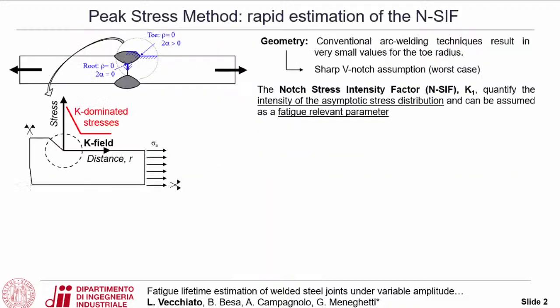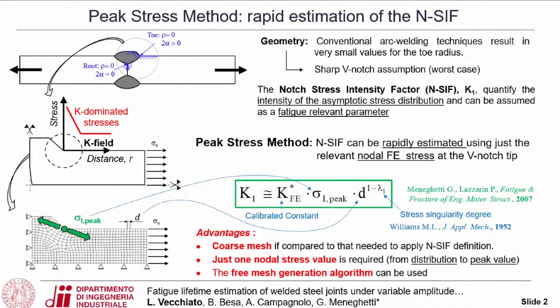loadings. Just to sum up what the method is related to, it's referred to local approaches for fatigue life assessment of welded joints, and in particular, it assumes that the weld toe and the weld root can be modeled as sharp V-notches. Accordingly, it has been shown by many papers in the literature that the notch stress intensity factor is a fatigue relevant parameter. And moreover, in 2007, Professor Meneghetti and Professor Lazzarin defined the so-called peak stress method as an engineering tool to rapidly estimate the NSIFs at the V-notch tip by means of linear elastic finite element analysis with a rather coarse mesh if compared to the one required for computing the NSIF by its definition given by Gross and Mendelson.